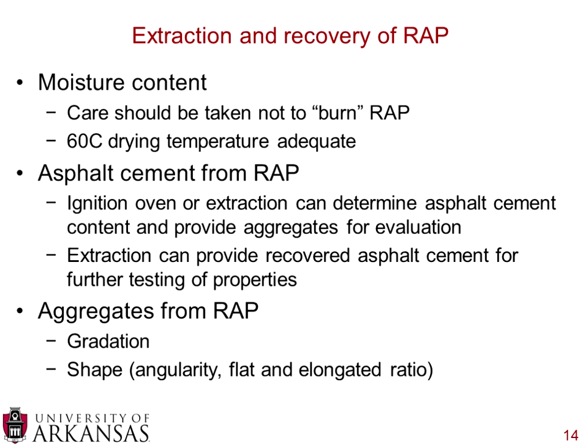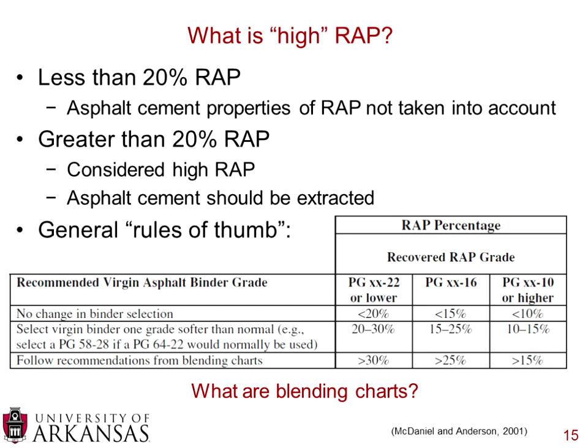Some of the information that's important for aggregates from the RAP is the gradation. You want to know what size distribution you have, and also the shape of the RAP, and that can include the angularity, the flat and elongated ratio. Often they have 100% crushed faces because the aggregate has been milled and recrushed, but the shape and the gradation are the two most important.